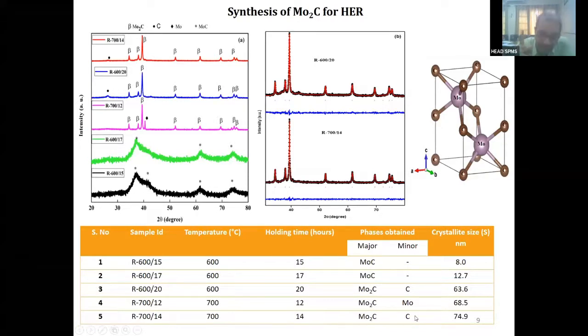Now, this carbon support is important. If you take Mo2C itself, it is not going to help to that extent as compared to Mo2C and the carbon both. Now, crystallite size, perhaps all of you know what it is. The crystallite size is lower for lower temperature synthesis and higher for higher temperature synthesis. You will find that the crystallite size increases from 600 to 700 degrees centigrade. This is the characterization part, and the structure I have already shown on the right side of the PPT, where you can see the molybdenum and the carbon atoms arranged over here. In this case, you will see that the c-axis is elongated.